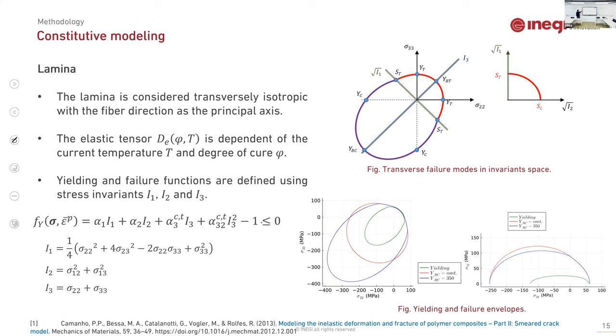How do I model the lamina? The lamina is considered to behave as transversely isotropic because you have the fiber, which is the principal direction, and the transverse direction, which is weaker. The elastic tensor has this similar behavior. We have an elastic tensor for the lamina that depends on the curing degree and the temperature also. And we have the yielding and failure behavior that is also considered.